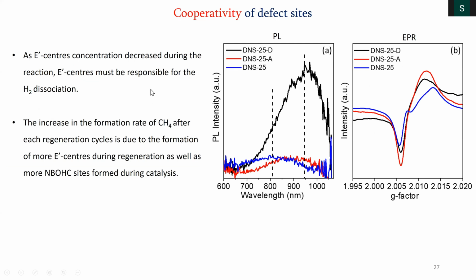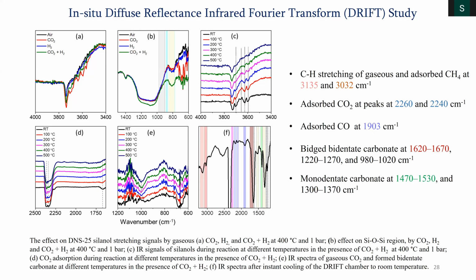And this particular data, which I will skip to save time, explains that every time you regenerate, you are producing more and more defect sites, and that's why you keep getting more and more catalytic activity. Yeah, so then we did this in situ diffuse reflectance measurement to understand which defect sites are interacting with CO2, which defect sites are interacting with hydrogen, so that we know who is activating CO2 and who is dissociating hydrogen.